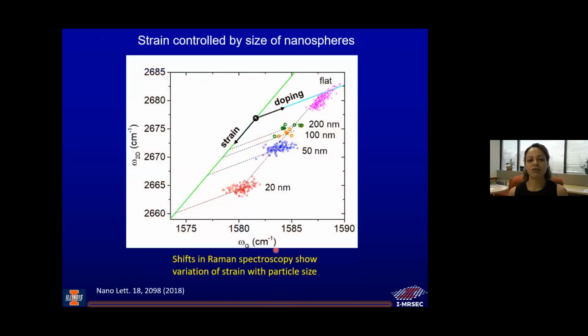We go back to this Raman spectroscopy. Okay, so we go back to the Raman spectroscopy, and you can see that we start with here's our strain line, right? Anything that moves along this line tells us that we're straining. Okay, and we start with our flat graphene. Okay, this is just a control device with no nanospheres, and this is what the ratio of the G to 2D looks like.